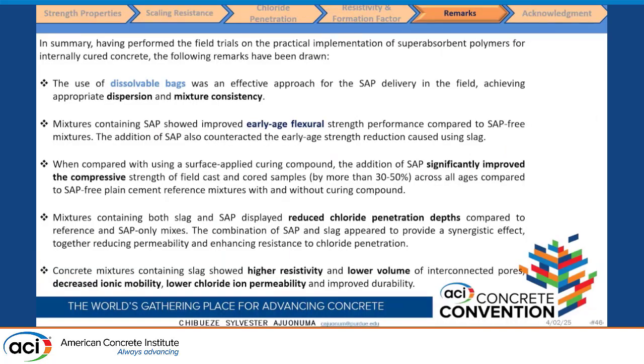Now, in summary, first of all, we found that the use of a dissolvable bag was very effective for SAP delivery in the field, achieving adequate dispersion and mixture consistency. Secondly, we found that the addition of SAP and slag helps to improve the early age performance of mixes, which, when we compare the SAP-free mix with the mix with SAP, helps to improve the early age reduction which is associated with some slag mixes.